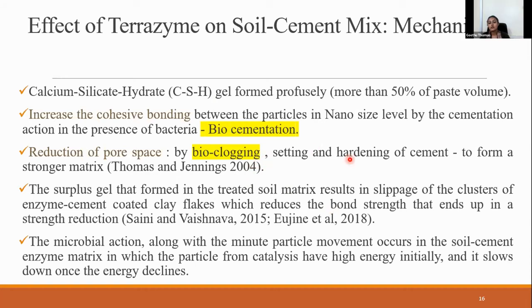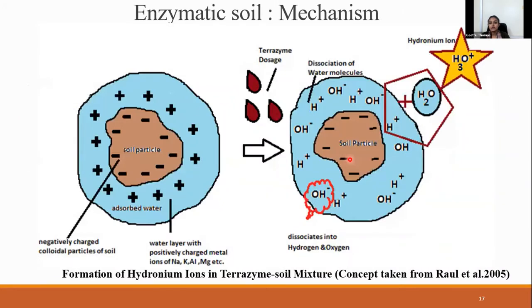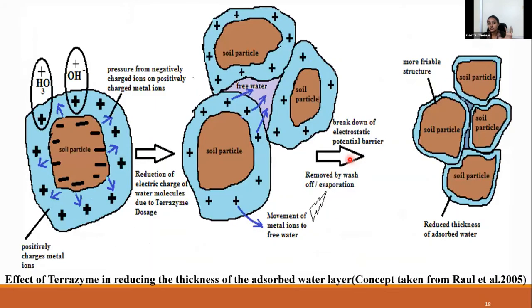But a surplus of gel, that means CSH gel produced beyond the optimum dosage, will result in a reduction in strength because the excess gel causes slippage between the soil particles. This is the illustration of strength improvement. That means the adsorbed water layer thickness is reduced because of the addition of enzyme, which makes the soil into a more friable structure with a less void structure.